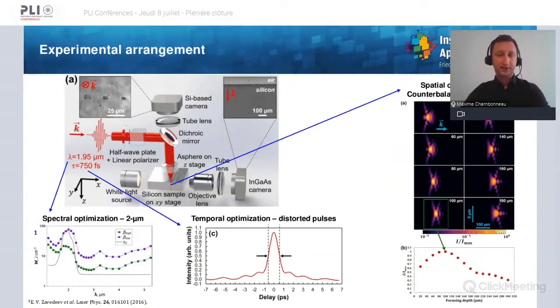Well, to answer all these questions, we rely on the following experimental arrangement, which is essentially the same as previously, except that now the input wavelength is around 2 microns, which is a spectral optimization, because then the deposited energy inside the material is the highest. We also work with 750 femtosecond pulses, but with distorted temporal profiles, as you can see with this AC trace here, which is a temporal optimization.